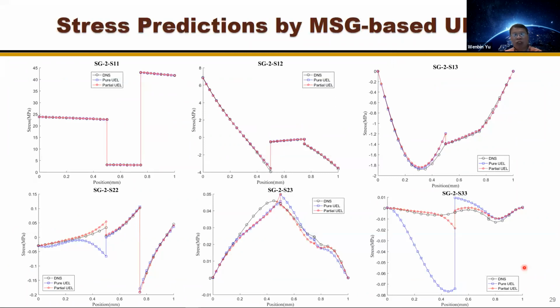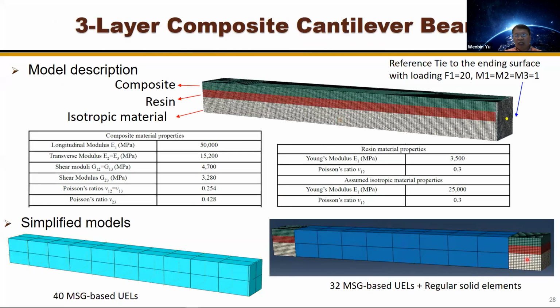And if you look at the results for this problem, we did a DNS, which meshes everything with a very fine mesh. And also pure UEL means 40 UEL elements. Partial UEL means at the two ends you have the DNS part and in the middle, this is partial UEL. And the results I take are here, very close to the boundary. Actually, if I take it at the boundary, then they are the same. But for pure UEL, they will be very different. But I take this section here, close to the boundary, but it's already homogenized.